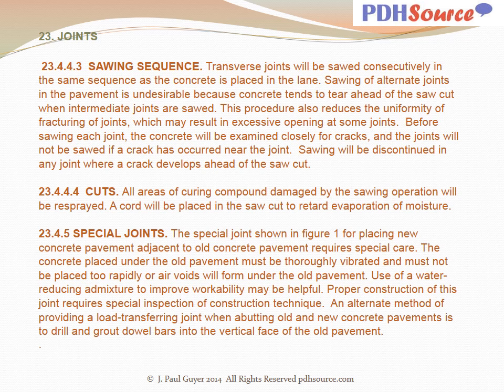Before sawing each joint, the concrete will be examined closely for cracks, and the joints will not be sawed if a crack has occurred near the joint. Sawing will be discontinued in any joint where a crack develops ahead of the saw cut. All areas of curing compound damaged by the sawing operation will be resprayed. A cord will be placed in the saw cut to retard evaporation of moisture.